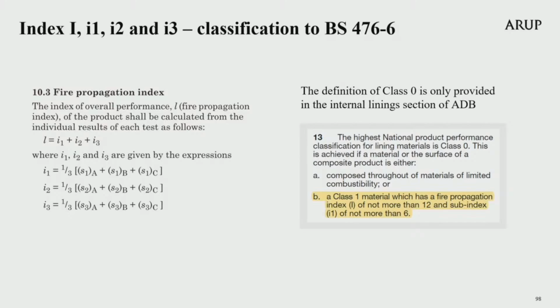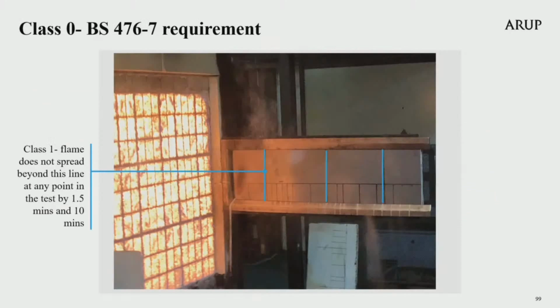Please now look again at the definition of class 0 on the screen marked in yellow. There it states for class 0, the fire propagation index must be not more than 12, and sub-index little i1 must be not more than 6. And so the test results from Part 6 on a material or composite product must fall within these limits. Additionally, the class value of 1 must be achieved when the same product is tested to Part 7. Class 1 means the flame must not spread more than 165 millimetres from the heated end after 1.5 minutes into the test. But in Class 1, it must not also exceed this limit for the entire duration of the test for up to 10 minutes. And I have shown you where Class 1 is located most closely to the radiant panel shown on the screen now.